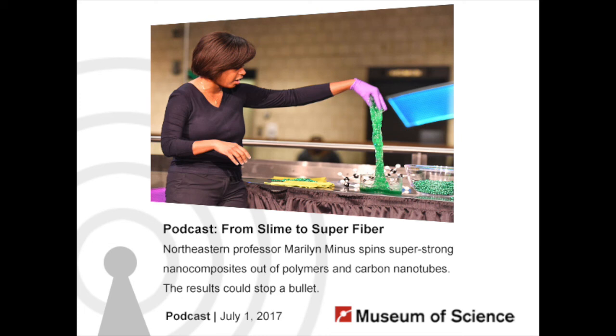And the reason that's important is each polymer chain, the chemicals that make that chain are a little bit different. So while they're all long chain polymers, because they have different chemistry, you have to tune the flow and the temperature just right for each and every one. And so we're trying to develop a universal process so that we can make basically strong fibers from pretty much any flexible polymer chain. Cool.